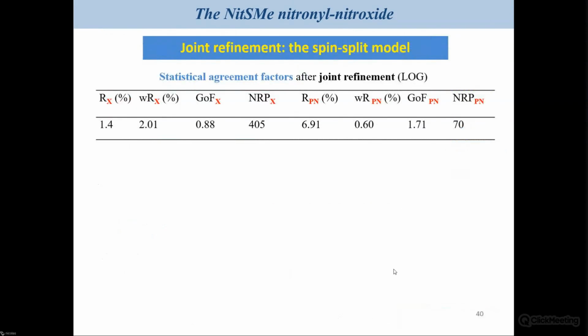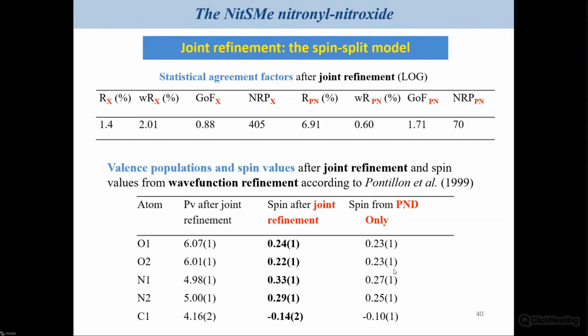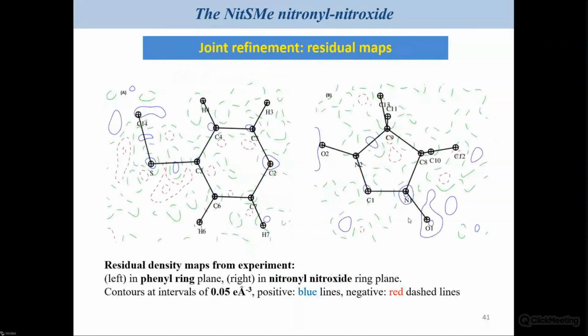Okay, so let me just describe what we obtained from that. We obtained very good agreement factors for both X-ray and polarized neutron refinements. And what is interesting, if you compare the spin populations obtained for polarized neutron diffraction only or for joint refinement, they are close, but they are not identical. You observe slight differences.